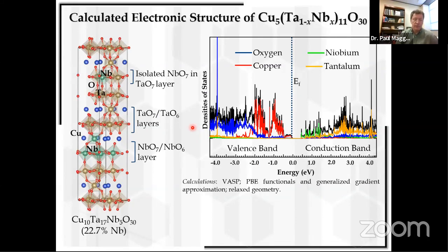And so we did electronic structure calculations again. And in this case, we have parts of the structure here in green, where I've put in extended networks of niobium, and another part of the structure where I inserted an isolated niobium, just to see where the states would emerge within the electronic structure here. And so I have here a densities of states plot of both the valence band and conduction band, and then the atomic orbital contributions to them. Okay, so the highest parts of the valence band, you see the predominant contributions are from copper. Now in the conduction band, we see contributions from both niobium at the lowest parts of that band, which is what we expect, and then tantalum from the highest parts of the band here.